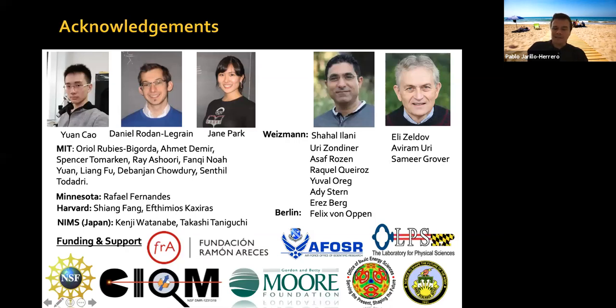Then a single device is being measured for many months, sometimes even a year or more at Weizmann. So this is a very slow process for characterization, and we cannot do this for each of the devices that we measure. We measure dozens of devices at MIT, and we don't have local angle information for each of them. So for that particular nematicity device, we do not have information on the local twist angle variation.